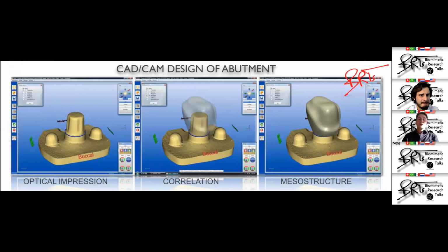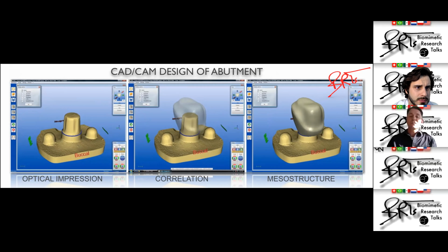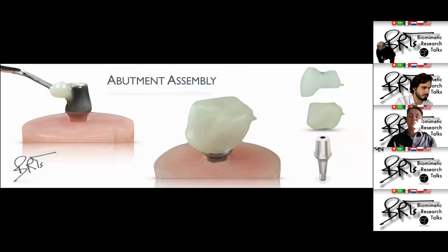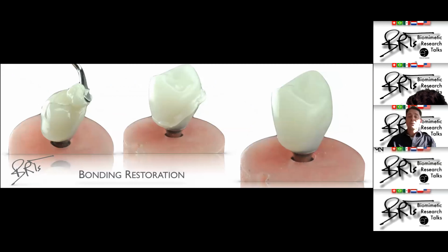In this experiment we had to build up the mesostructure. So we went to CEREC again, and in the correlation mode, we copied the ceramic abutment and built what we call the mesostructure. This mesostructure was milled in composite resin and bonded over a metal link with the bonding procedure: we sandblast, use OptiBond FL, and preheated Z100 composite resin. Once the abutment was ready, we bonded the restorations. So we bonded composite and ceramic restorations over those hybrid composite abutments. The samples were ready for loading.